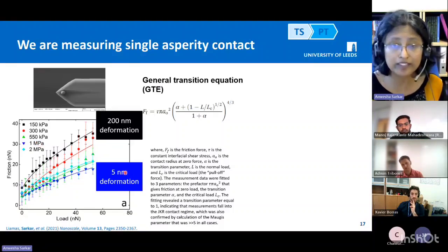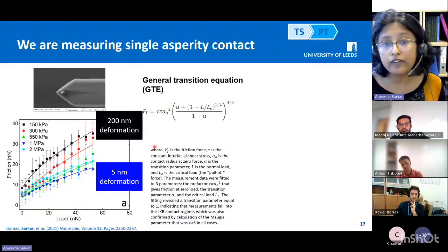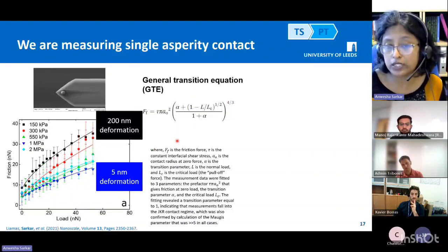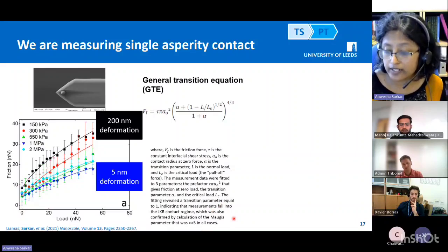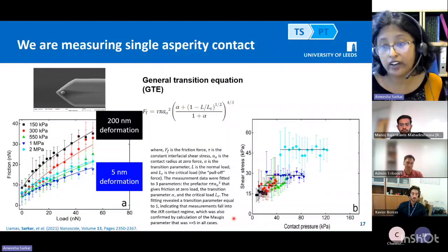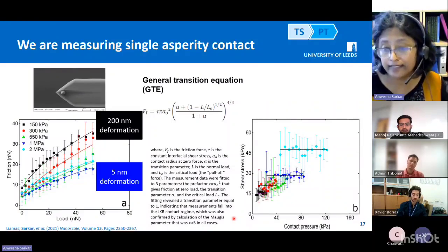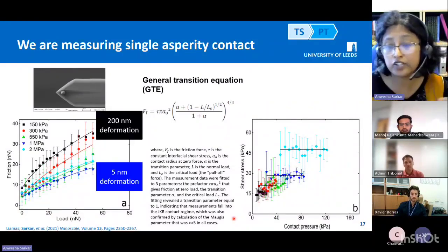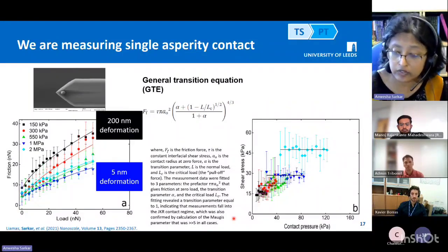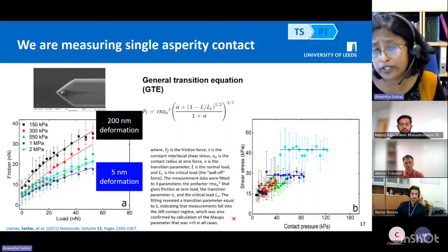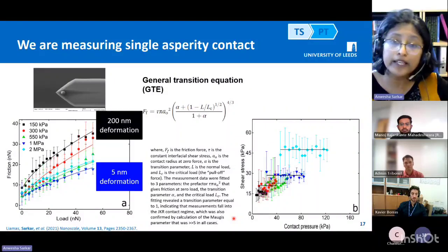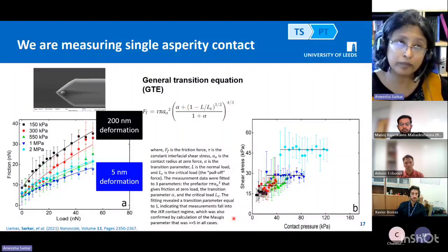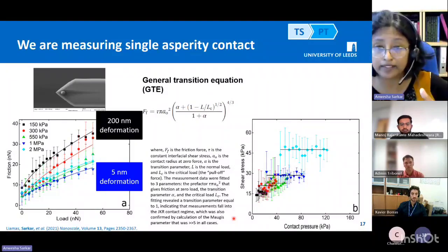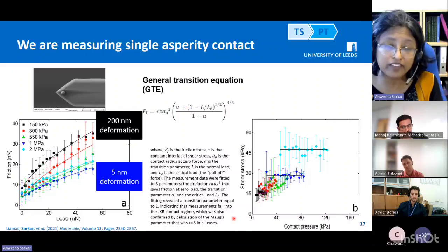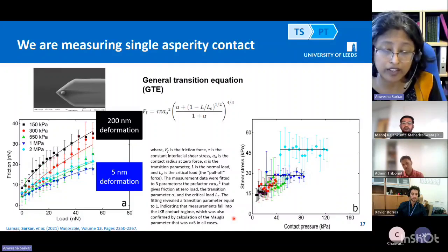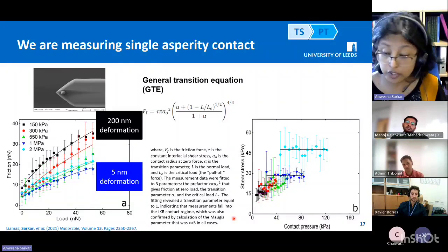And that matters because that matters in perception. And when we fitted it into a DMT model, what we identified was it was actually falling into the JKR regime. So basically, adhesion mattered a lot in these kind of systems. Why is it important? I will quickly show you in an example that both these measurements are important, the tongue scale and the single papillae scale, because the kind of behavior that happens with proteins in the mouth are very localized sometimes, and I will show you why.